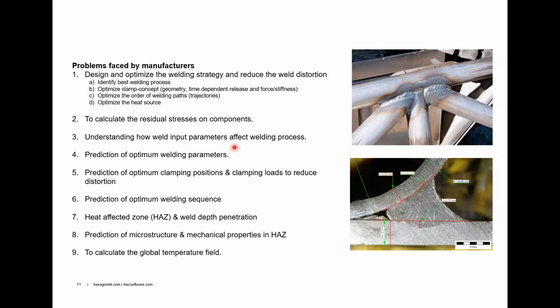Okay, and then it can be prediction of welding parameters, then prediction of optimum clamping positions and clamping loadings to reduce distortion. Okay, and we can study the heat affected zone or the weld depth penetration. So these kinds of studies can be made. If you see here on the weld macrograph, you can see the weld penetration or the fusion zone, or how we can model this fusion zone in our software, and we can see the heat penetration, or whether the fusion is happening, or whether a burnout is happening at that area. These kinds of things we can study.